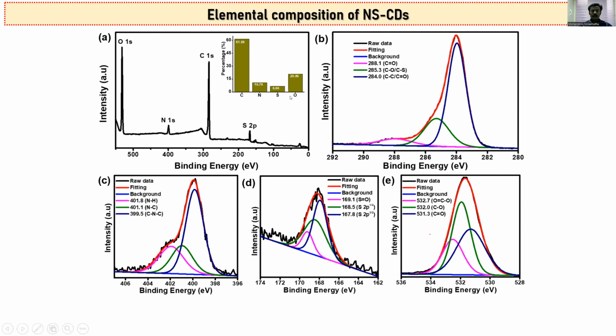Okay, and then we have the peak fitting for carbon and other sources. We can get C double bond O, C single bond O and C single bond S. We can also get the carbonyl group, with binding energies of 288, 285 and 284 electron volts. Okay, the next one is nitrogen. There are 3 different peaks, at 401.8 for NH. We can also confirm this from the peak fitting analysis.